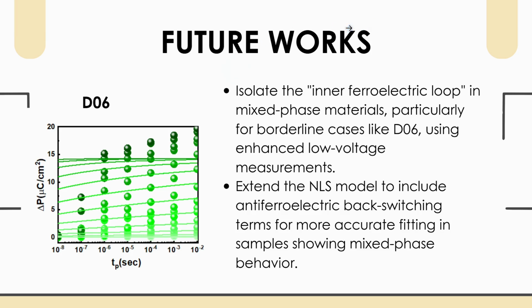And lastly, the future work that I plan to do. I'm going to isolate the inner ferroelectric loop in the mixed phase materials, particularly for borderline cases like D06, using enhanced low voltage measurements, and then extend the NLS model to include the anti-ferroelectric back switching terms for more accurate fitting in samples.